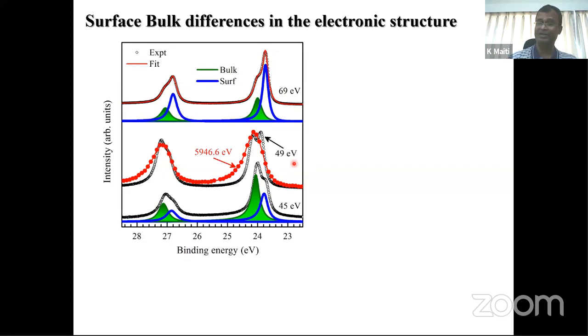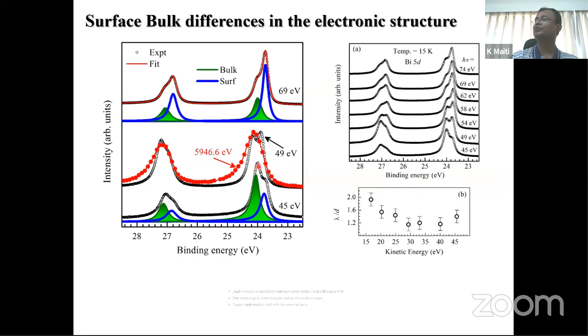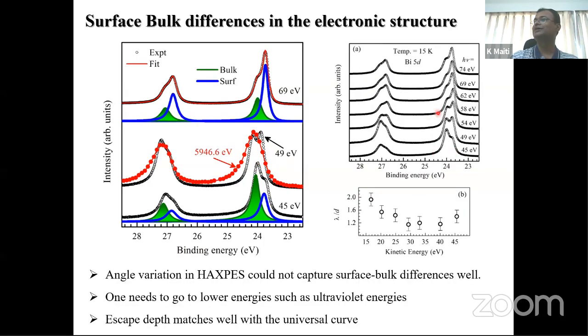But here it's very, very narrow. And that's the reason you see that only when you become extremely surface sensitive, then you see surface and bulk peaks separately. And we can, of course, study it by changing photon energy and find out the effective penetration depth, where the maximum surface sensitivity is of the order of, say, 6 angstrom or so, at around 35 to 40 electron volt kinetic energy. Okay?